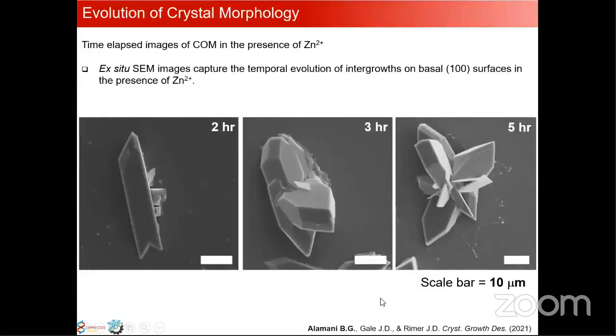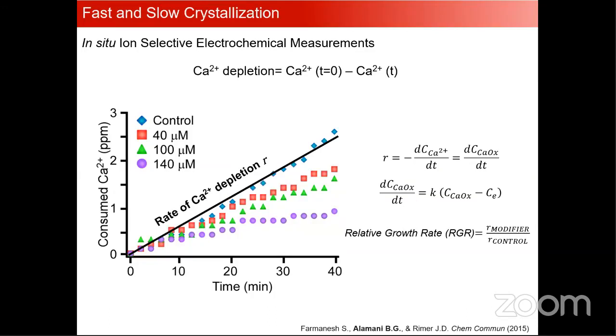This one, the intergrowth. We tried to do ex situ time-elapse analysis to see whether they actually grow. So here we had a time-elapse visualization taken using scanning electron microscopy to see where those crystallites originate. They appear to originate on a young crystal here, and then this one protrudes towards the C direction. Slowly it evolves, forming this dendritic-like structure, which we call intergrowth in our studies.